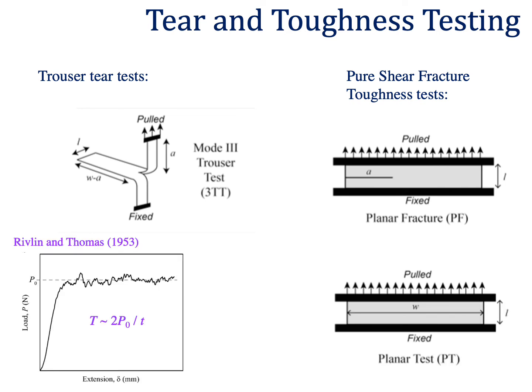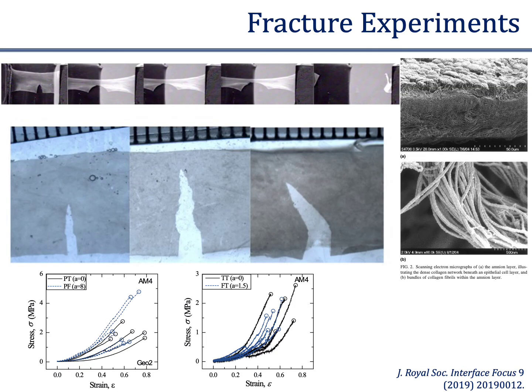The analyses for both of these types of tests were actually considered quite a bit in Rivlin and Thomas's 1953 masterwork on the fracture of rubber. And so the analyses for these are pretty straightforward in that they have been considered before. And in the case of the pure shear specimens, we use an unnotched control specimen along with the notched specimen to calculate the fracture resistance.